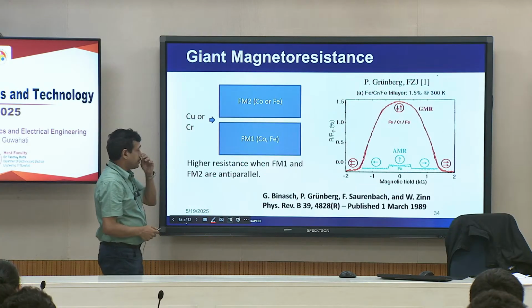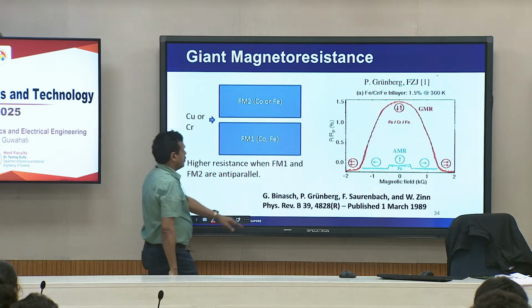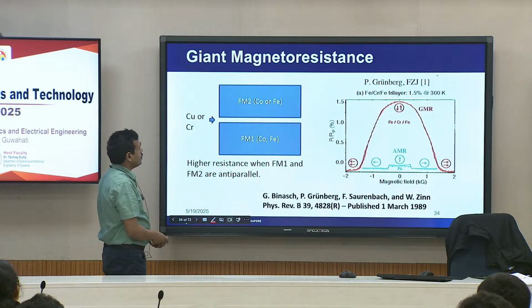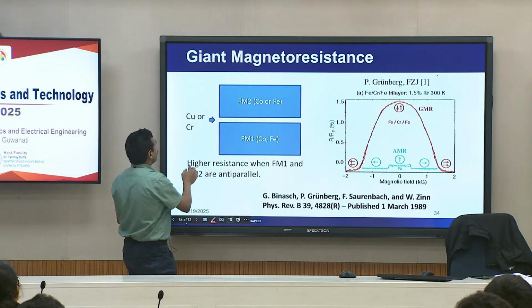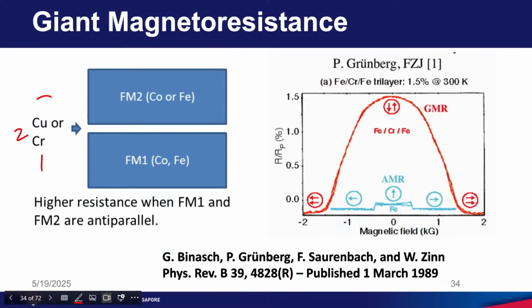You will see an almost similar result observed by the group of Professor Grunberg. Here they do not have 60 layers or 30 layers, they just have 3 layers. 1, 2, 3. The ferromagnetic layer is iron, the second ferromagnetic layer also is iron, and the layer in between is chromium. Here again they see a similar result. When the magnetic field is 0, resistance is high, and when the magnetic field is large, resistance is low, and again when you apply magnetic field in the other direction and it is large, you see low resistance.